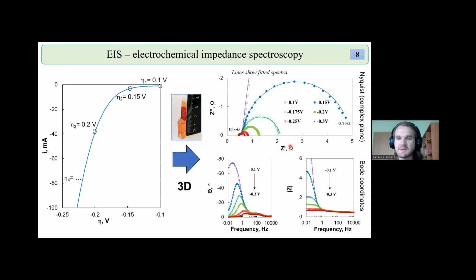The spectra are characterized by two important features: a high frequency response here, which is very small, and relatively similar when obtained at all overpotentials. And the low frequency response, which is the larger semicircle. And it can be seen that the magnitude of this semicircle decreases significantly with applied overpotential.